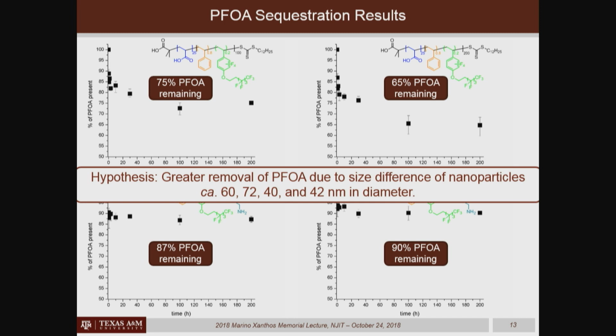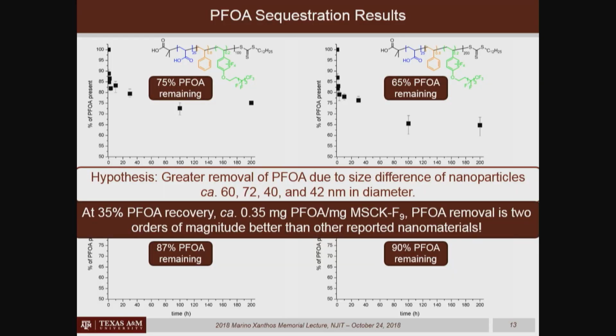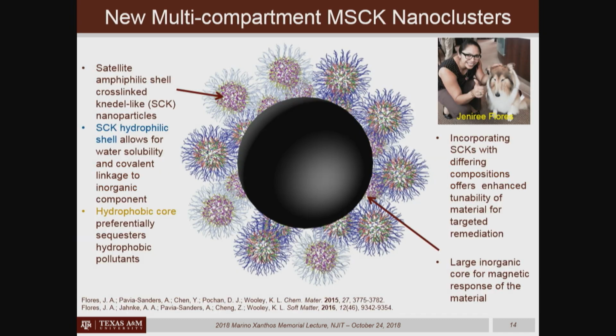So even though these numbers don't look great, when I say 10%, she was using a 1-to-1 weight-to-weight balance. And so that's still taking up, say, 0.1 milligrams of perfluorooctanoic acid per milligram of our material. And so at the best case, where we were able to take up 35%, that's 0.35 milligrams of perfluorooctanoic acid per milligram of these magnetic shell cross-linked Knedel-like nanoparticles, and that's still 2 orders of magnitude better than comparable nanomaterials.